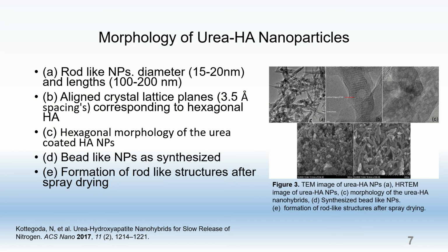Now, this slide shows the morphology of the urea-hydroxyapatite nanoparticles, and in figure 3a shown here is a TEM image of the hydroxyapatite nanoparticles, and what it reveals is they have a rod-like shape with diameters between 15 to 20 nanometers and lengths ranging from 100 to 200 nanometers. The high-resolution TEM image shown here in figure 3b shows two distinct phases, the urea phase and the lattice fringes of the hydroxyapatite. The lattice fringes are perfectly aligned with a spacing of 3.5 angstrom, which corresponds to the interplanar spacings of planes for hexagonal hydroxyapatite.